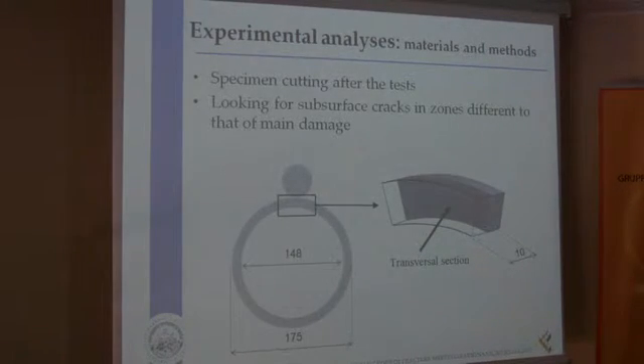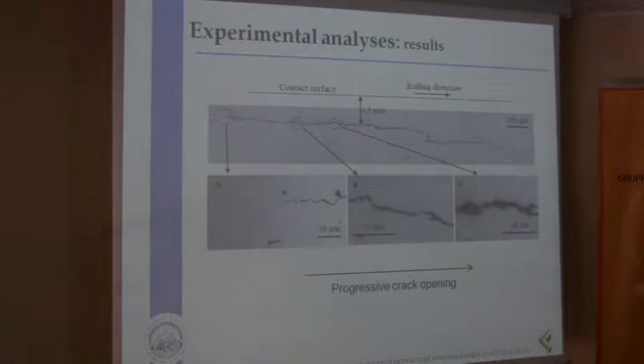After the test, the specimen was cut along its transversal section and examined by optical and electron microscope, in particular looking for subsurface cracks different from the main one, so different from that causing the macro spalling, in order to study the damage evolution in an intermediate state. Thus, we found different subsurface cracks, and this is a significant one, representative of the behavior of the other cracks.